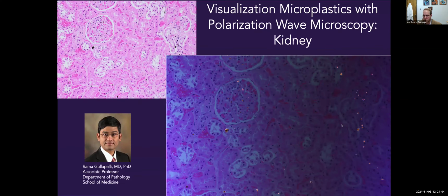So this isn't 100% saying these are plastic, but we have a hunch that they are plastic. And it's interesting because when we look at these, you can see these bright spots lighting up. You don't really notice them in the H&E until you do this polarization technique, but we see them largely in the glomerulus as well as along the distal tubule.